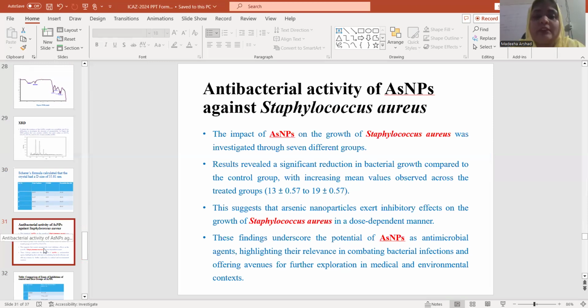Antibacterial activity of arsenic nanoparticle against Staphylococcus aureus. The impact of arsenic nanoparticle on the growth of Staphylococcus aureus was investigated through 7 different groups. Results revealed a significant reduction in bacterial growth compared to control group with increasing mean values observed across the treated groups. This suggests that arsenic nanoparticles exert inhibitory effects on the growth of Staphylococcus aureus in a dose-dependent manner.